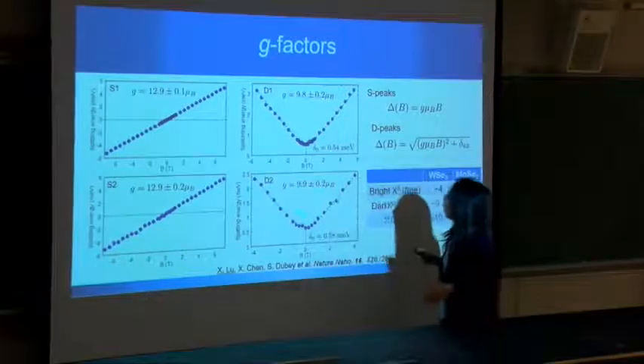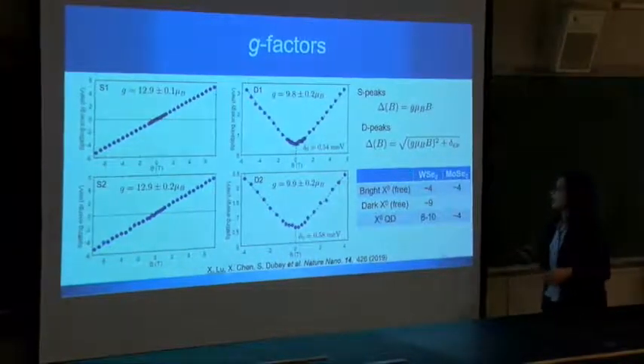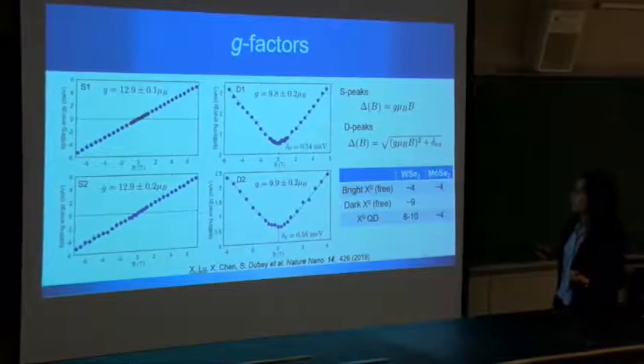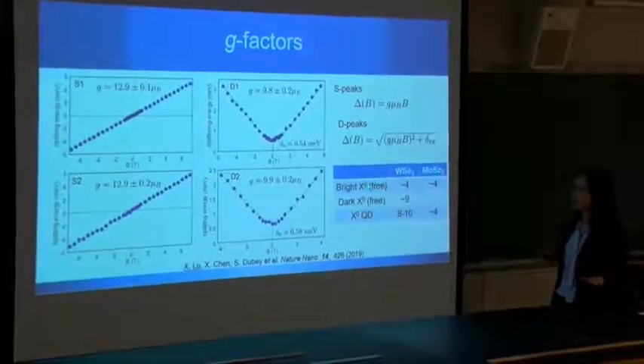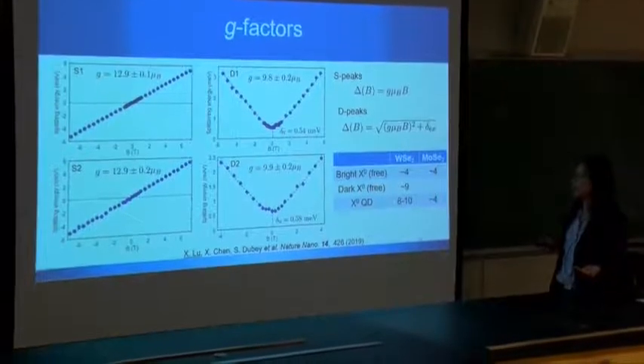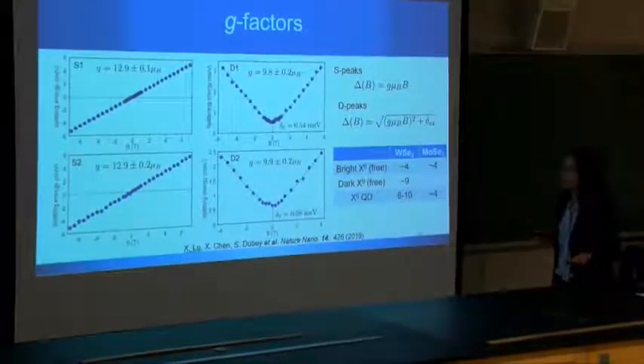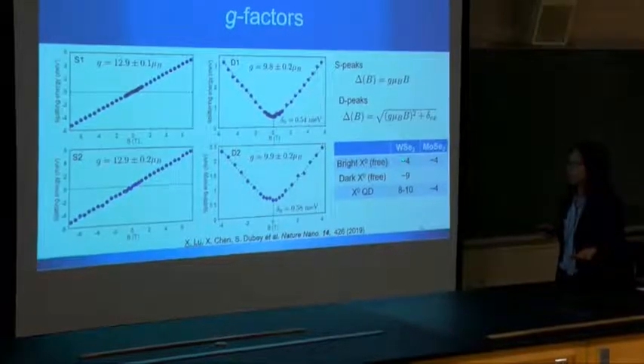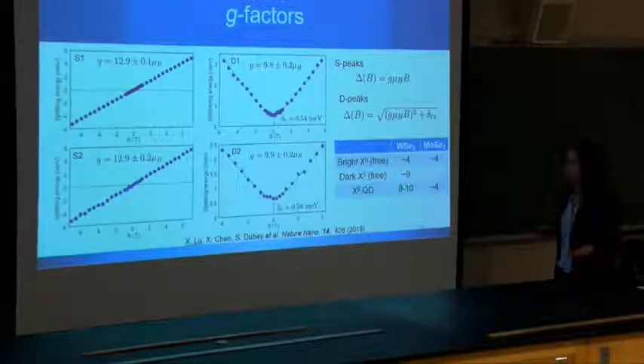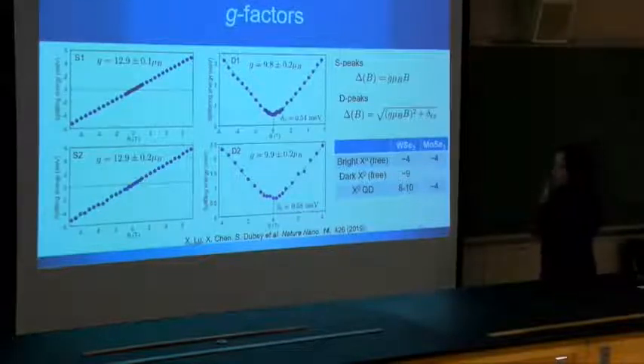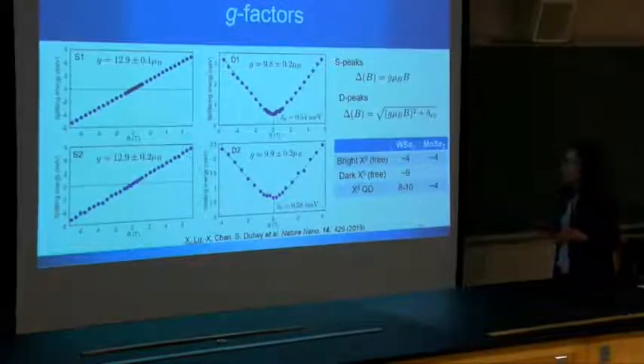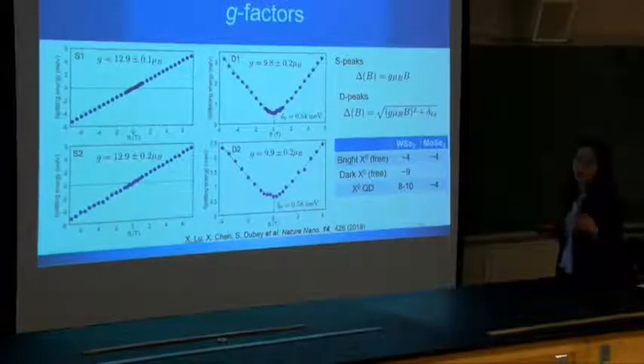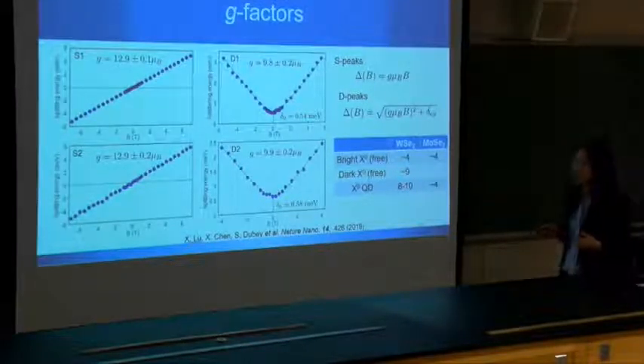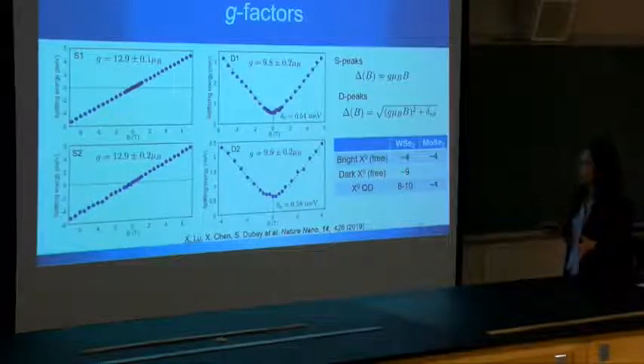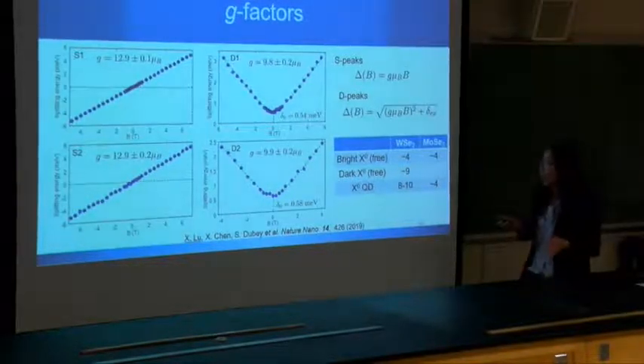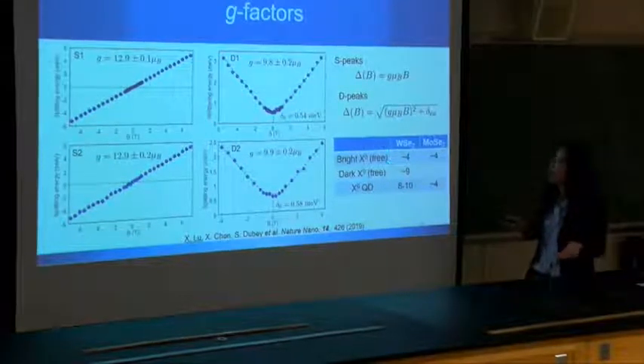And on the other hand, we do notice that in terms of G factor, let's say for molyselenide, no matter whether it's delocalized or quantum dot, it has a similar G factor. But for tungsten diselenide, there is a difference. For delocalized, it's around 4. But for a quantum emitter, it's larger. So why is that? We are actually thinking in our group that probably it's related to these localized excitons or single photon emitters actually being from dark exciton. But that could be the details here. And one can actually do a measurement to confirm that.